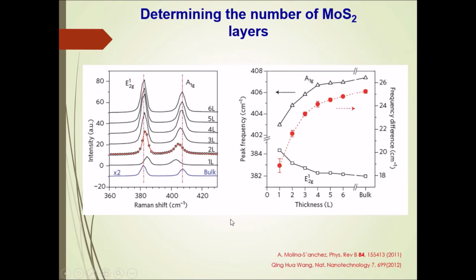Also, using Raman spectroscopy, or especially microspectroscopy, we can distinguish the number of layers in molybdenum disulfide. Molybdenum disulfide also has a hexagonal structure like graphene, but it's a semiconducting material. So we can find if we have monolayer, bilayer, 3 layers, 4 layers, 5 layers, 6 layers, only by calculating the difference in position between the E2g mode and A1g mode, and in this curve we can see a relation between the number of layers and the difference between these two phonons. In case of monolayer, we have about 18 or 19 cm^-1. Here we have about 21 in case of bilayer, till we reach bulk molybdenum disulfide.